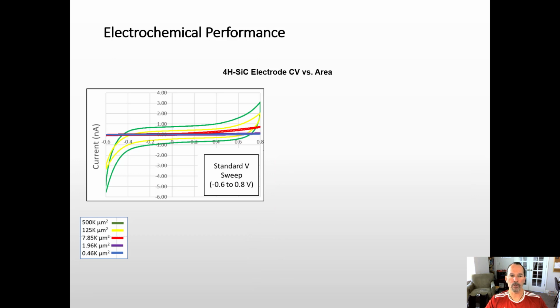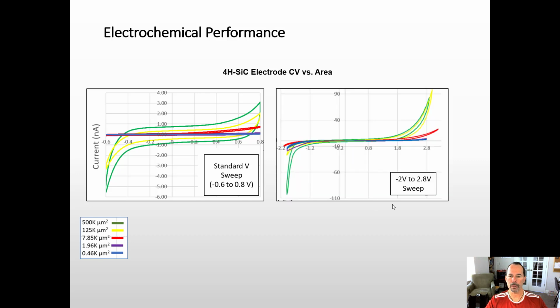So we continue our CV story looking at the CV profile as a function of area. We show that here: green is the largest area device, which of course shows the largest hysteresis, if you will, which means charge storage capacity, and blue is hard to read here. It shows our smallest. But what's interesting about silicon carbide, we're doing our standard platinum electrode sweep from minus 0.6 to plus 0.8 volts. If we look at 4H silicon carbide, due to the wider band gap, we can go from minus 2 to plus 2.8 volts easily.